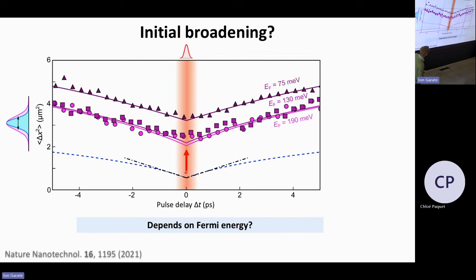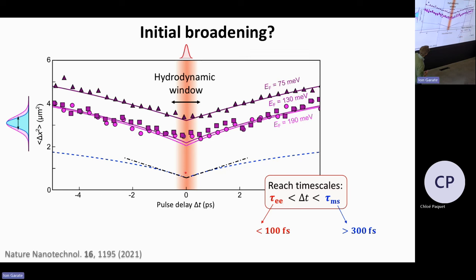In any case, we wanted to look at what's happening here in the center. And now the important thing to realize is that in the center, you're in a quite special regime time-wise, because we have a time resolution of about 100 femtoseconds. That's our delta T. We have electron-electron interactions that take place on a time scale of tens of femtoseconds. And we measured our momentum relaxation time, which is on the order of a few hundred femtoseconds. So we can probe the system at a time where the only interaction is between the electrons, but there's no interaction yet with any phonons. And that is a hydrodynamic regime because you only have electrons interacting with electrons.